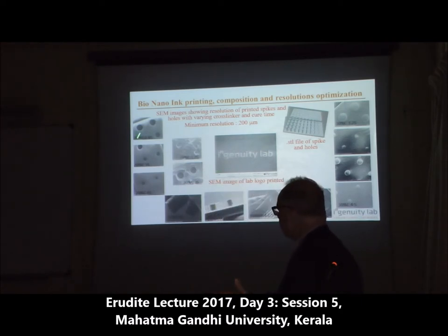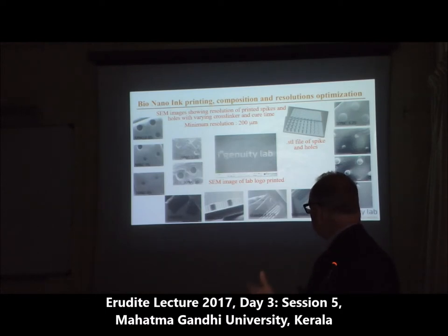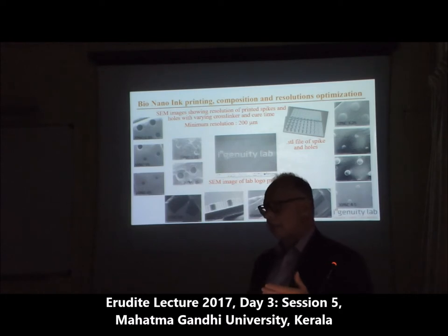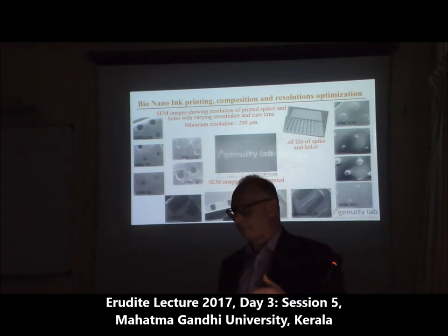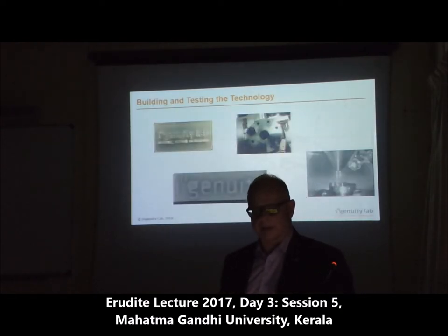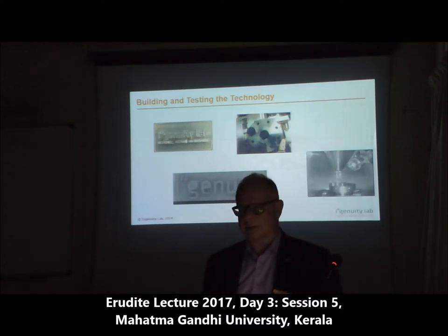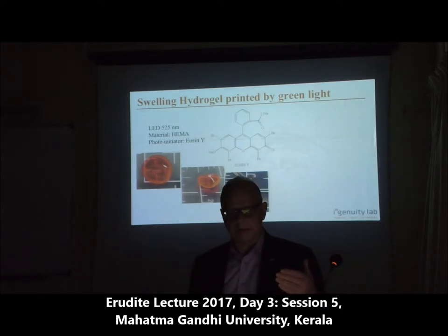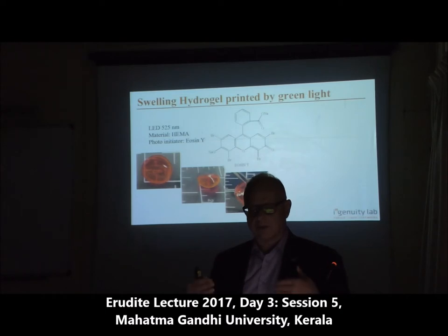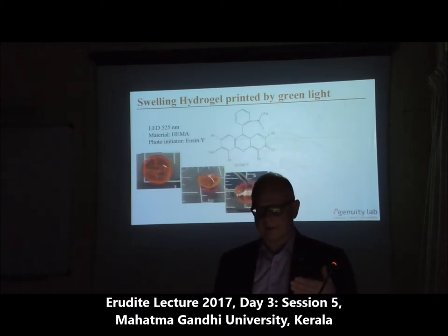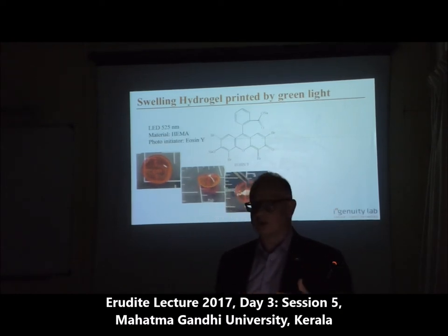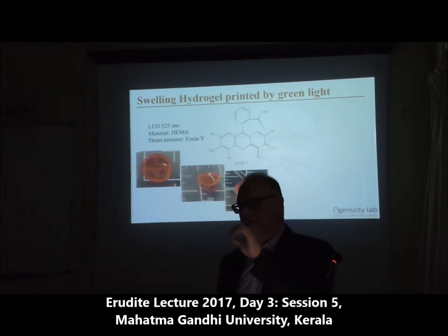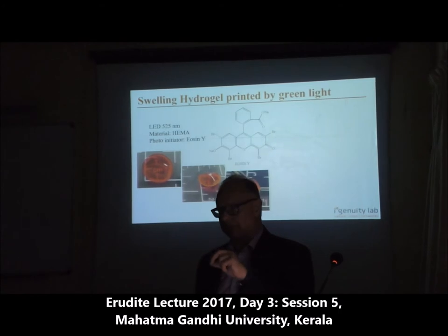Here you're looking at a series of arbitrary images made using different levels of exposures. We're able to get a minimum resolution of about 200 microns. We also have a nanoscribe which will supposedly give us 200 nanometers of resolution. Here you see one of the hydrogels made with green light, using material engineered by Stella, and it shows we're able to get it to polymerize with green light. The red light ones are still a challenge — exposure times are too long, you end up with materials that don't fully cure, and they don't maintain dimensional stability. So we're still working that problem.